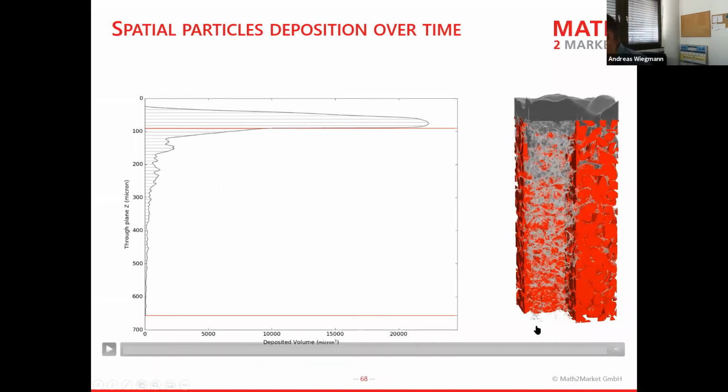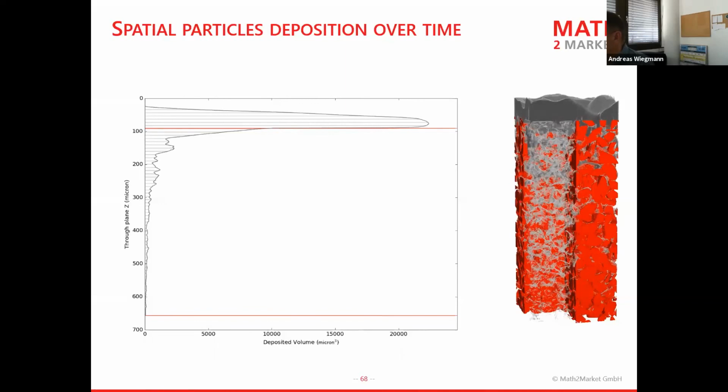The soot that went all the way down here and is visualized here has traveled in early stages of the simulation all the way down to then only finally get trapped by touching one of those grains very close to the outlet. It almost made it out there. This was in the initial phases, and you will have some, I don't know the word in English, at the very beginning in filtration, many times you have a little bit of particles going through and later everything gets filtered.